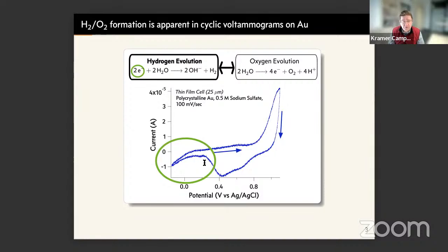The idea here is that if you start on the lower portion and scan the bias negatively, the current drops off negatively, and bubbles of hydrogen start to appear on the electrode. If you then switch scan directions and go back positively, there is this little bump at about 0.6 versus silver chloride. This is real, and perhaps the oxidation of the first monolayer of gold. If you continue positively, gold is oxidized. And if you continue still more positively, you start to oxidize water, and bubbles of O2 appear. If you then come back, you would see this negative current feature. This is just the reduction of this gold oxide. So it's quite clear that in a fairly simple experiment, we can see, at least on gold, the production of hydrogen and oxygen.